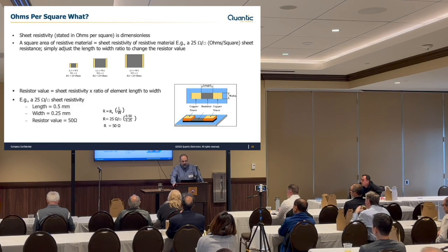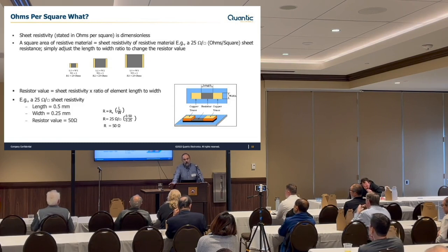So that's kind of the idea. So when we tell people ohms per square, they say, ohms per square what? No, it's just ohms per square. And so what you do is you control the geometries to get the resistance value you want. So if you want to go, as an example down here, to 50 ohms with a 25 ohm per square material, you just make it a 1x2, so basically 2 blocks. So it's all about the ratio of length to width.